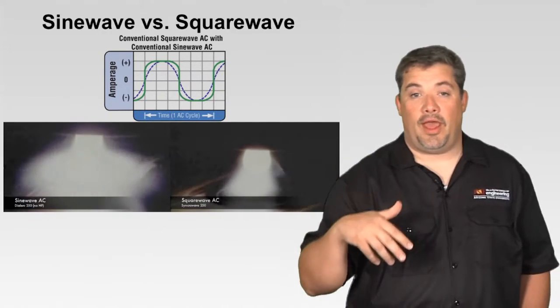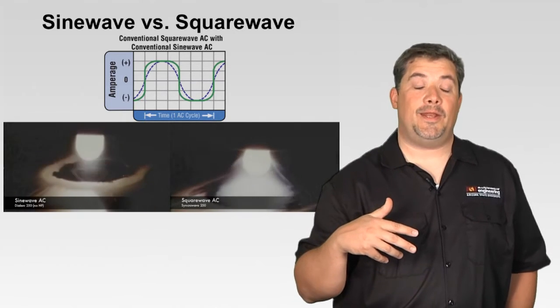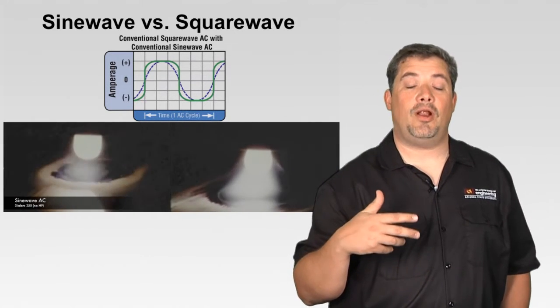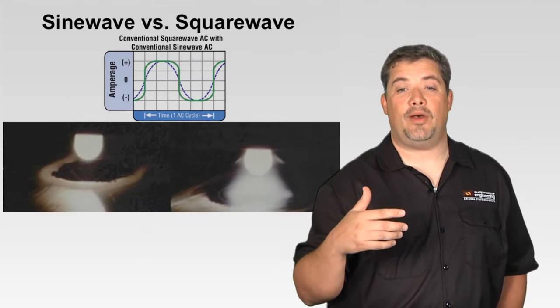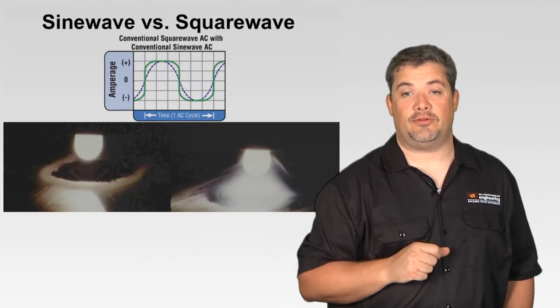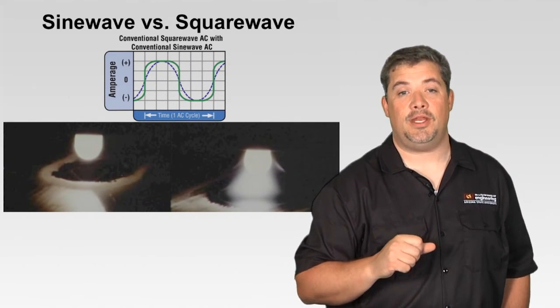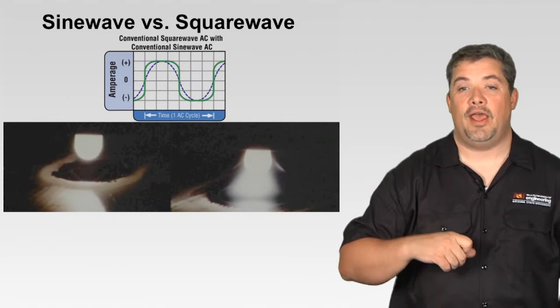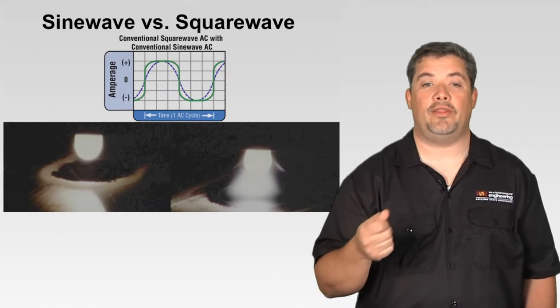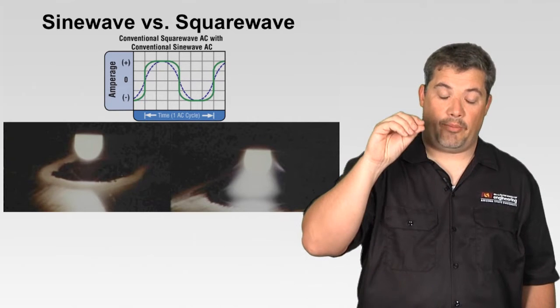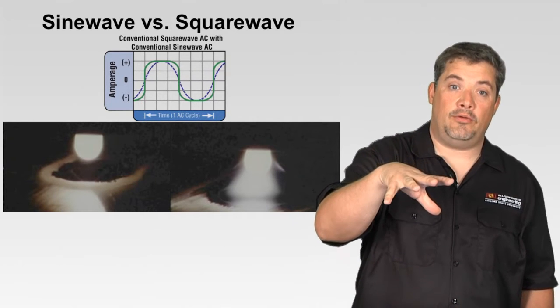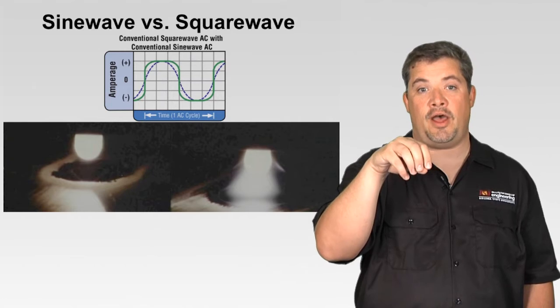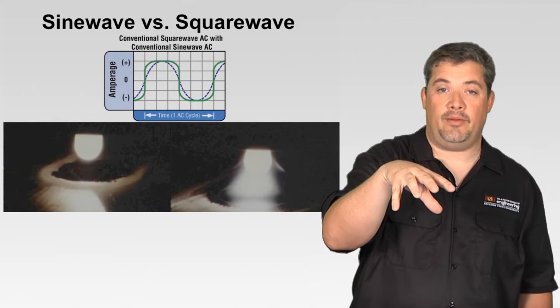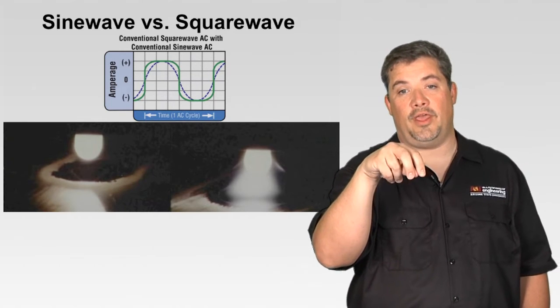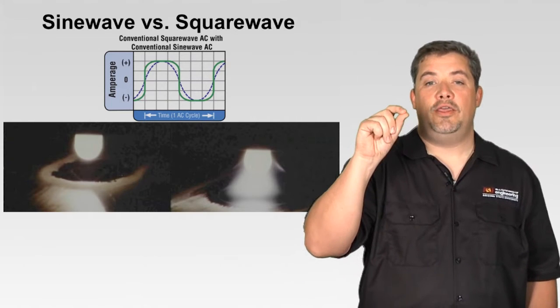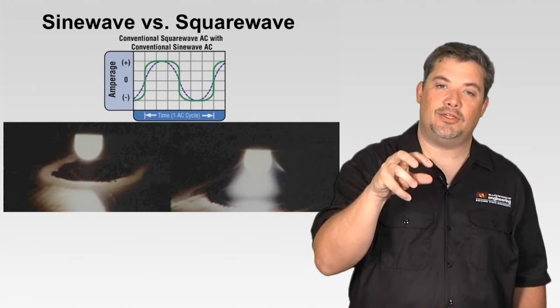Then we talked about that big advancement in 1976, where we created a square wave AC arc. This was the monumental thing. In these two illustrations, you can see the big difference between the sine wave on the left and the square wave on the right. On the sine wave, the amperage rises, peaks out, then slowly backs off, shuts off, reestablishes itself, rises up, comes back down, shuts off again, whereas on the square wave side, you can see it almost instantly make that transition through zero.